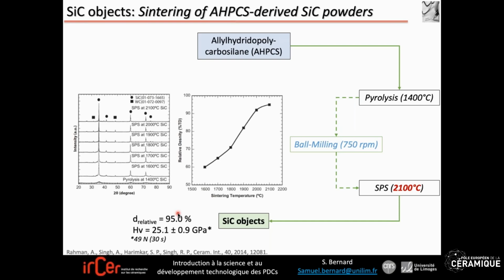So in the introduction, I said that this strategy is really interesting only if the PDCs route offers added value compared to the conventional process starting from powders. And here I would say that is not really the case, because you still need to apply the very high temperature of sintering to densify your silicon carbide, as it is applied using conventional process.